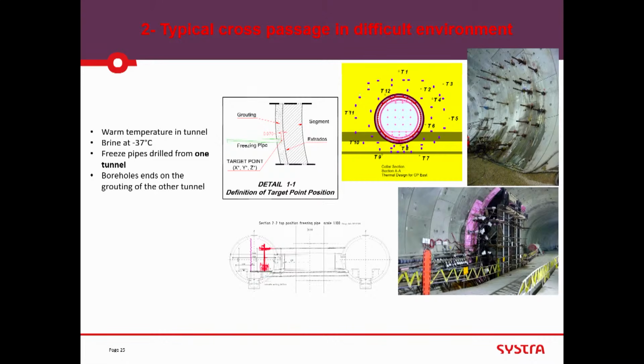And what we discovered, it was not easy, is that there was one pumping well still working at the end of the tunnel, in the box next to the tunnel. So the contact grouting with the segment was not perfect, as it usually is, not so perfect. Water was flowing. We were not able to freeze. And this was discovered because, in fact, we had enough instrumentation, measurement of temperature inside the body of frozen soil.